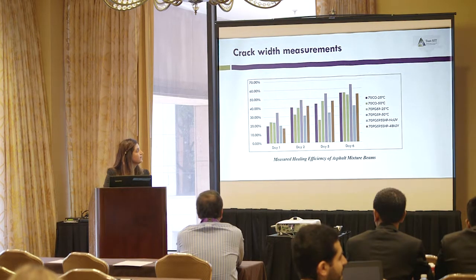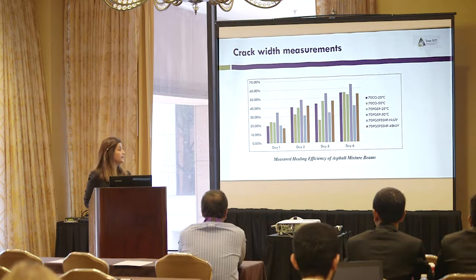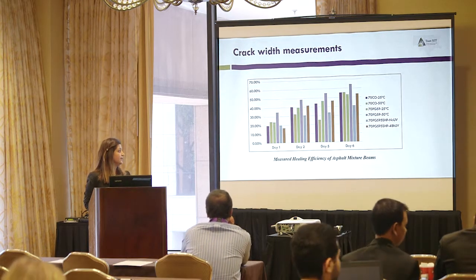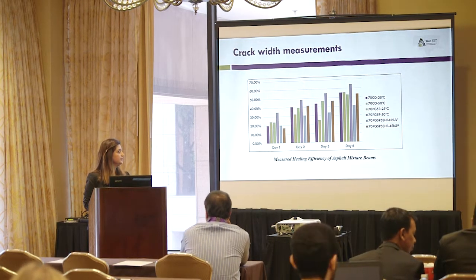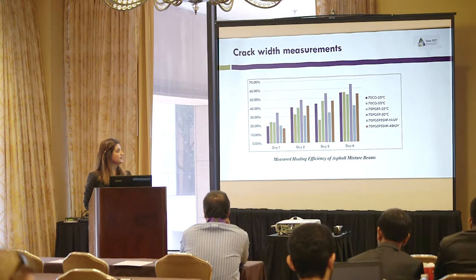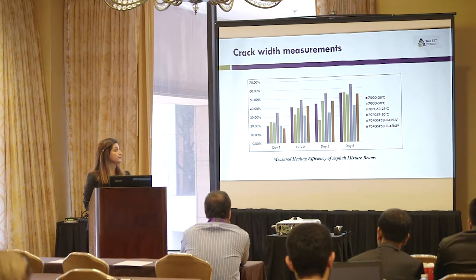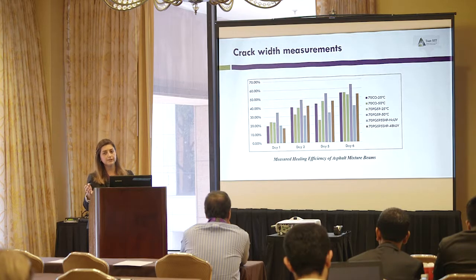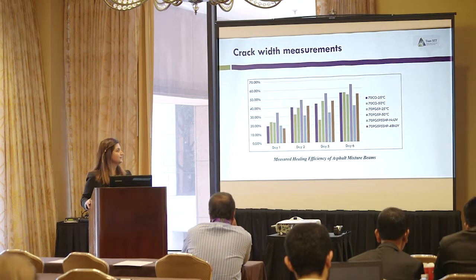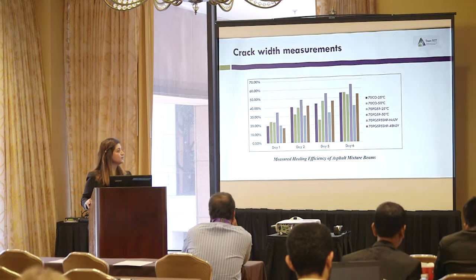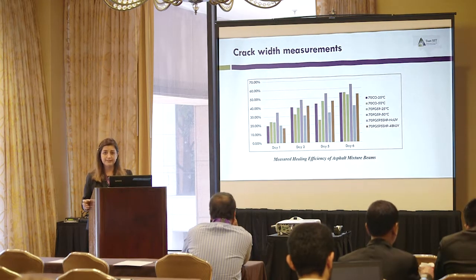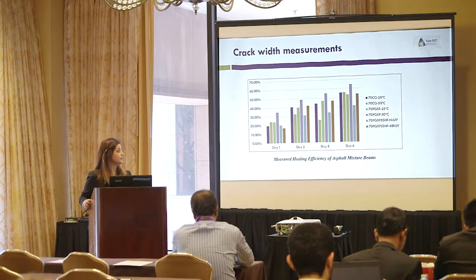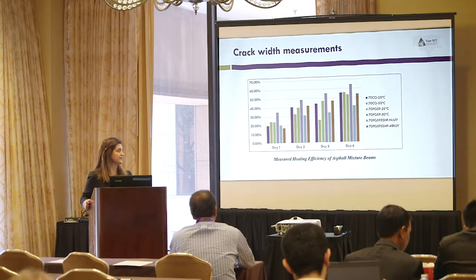And this is the result from crack width measurement and the image analysis of cracks under the beams. Again, we can see improvement in the self-healing performance of mixtures with exposing our samples to UV light, but the best performance belongs to the sample that has 5% RAS and a curing condition of 50 degrees C.